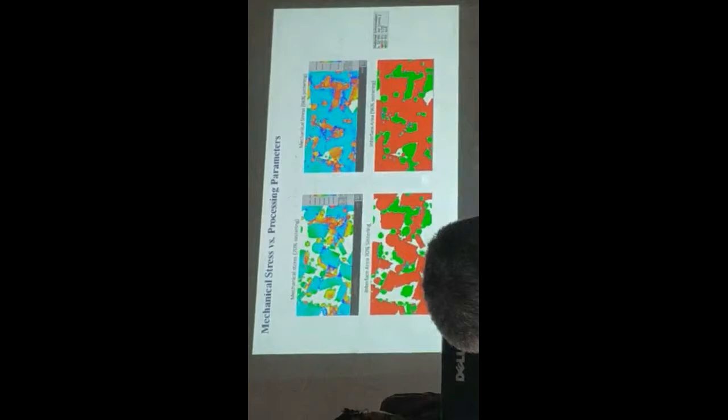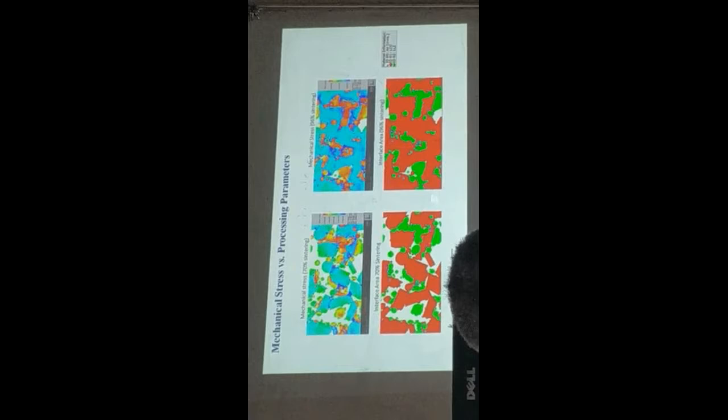But why? The blue dash is the surface area between the LCO in red and LLZ in green. The black dashes are the surface area between the LCO and the pores. So our equation is K factor equal to the surface area between LCO and LLZ divided by the whole area, namely the LCO to LLZ and LCO to pores.